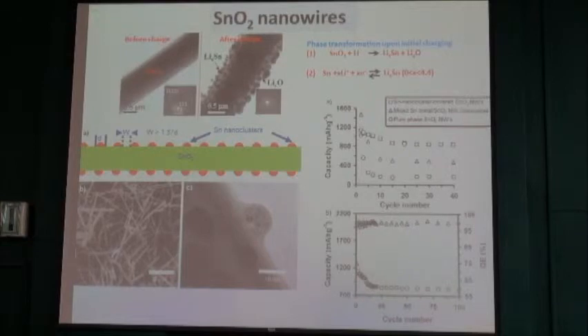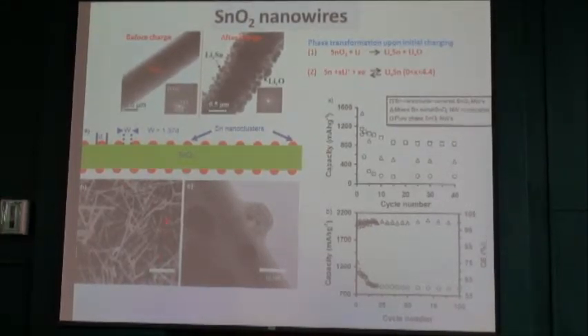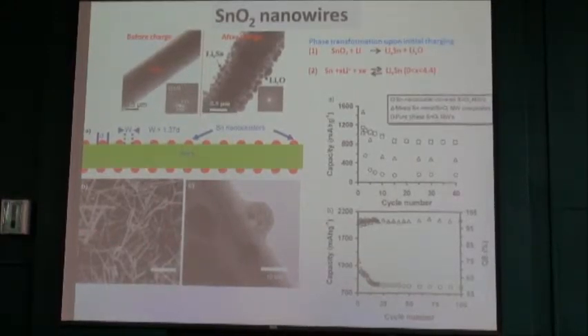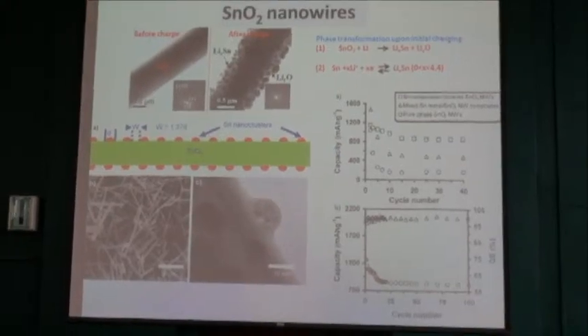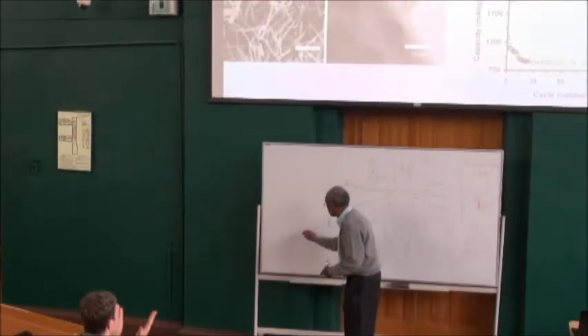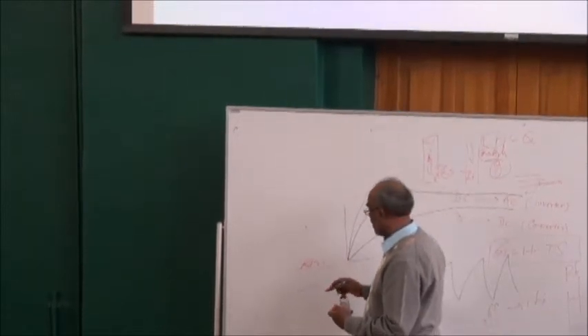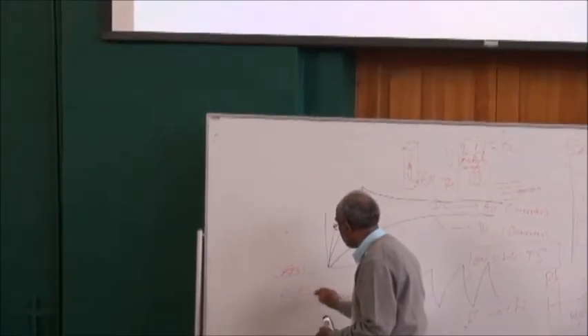The whole idea is that when lithium goes in, they try to expand, right? That's like 300% expansion. But when you have these metal clusters, they take some of that expansion stress. That way we can keep the nanowire intact. They don't collapse. The important thing is to have enough separation because they should not combine together. If I have them too close, then when they expand, they become one cluster. Then again it's like a thin film, so it doesn't help. We need to make sure they are well separated so that they don't merge together.